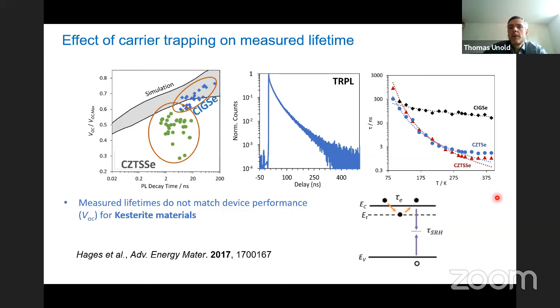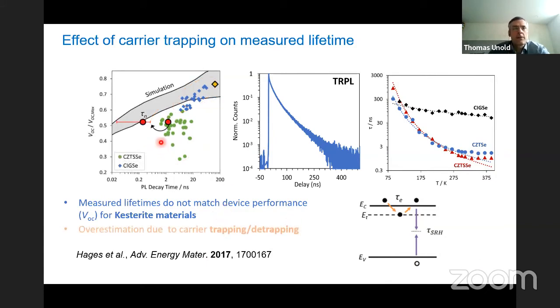And that depends on the temperature. And it means that if you do a temperature dependent measurement, then this lifetime should actually increase a lot if you go down in temperature. And you see that for CIGS, there's not so much change, a little bit, but for kesterite, it increases enormously. So at low temperatures, you get huge lifetimes. On the other hand, if you go higher in temperature, the lifetimes get smaller and smaller. And so from this, we concluded that the actual lifetime was always much smaller than the measured ones.